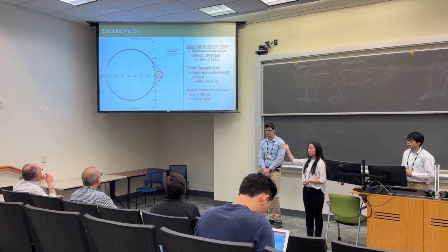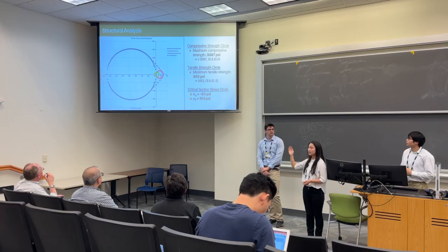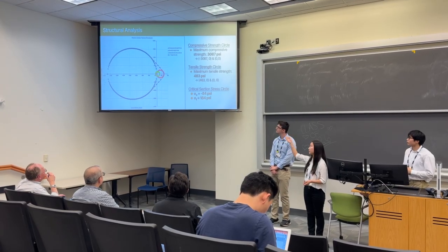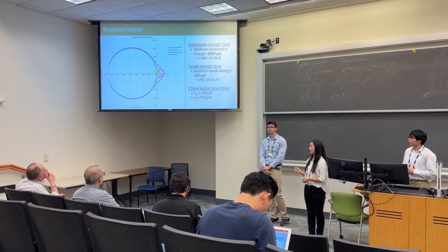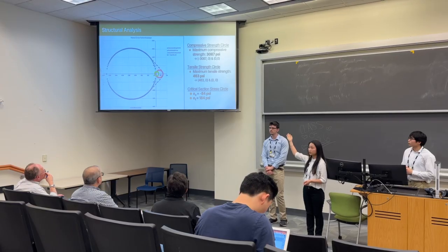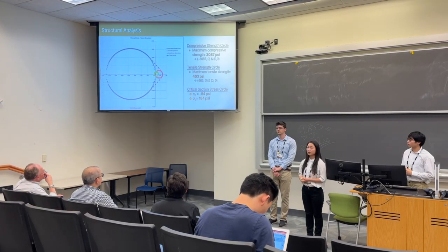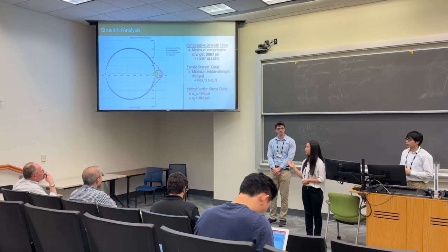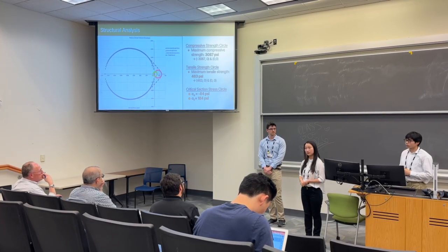And as you can see from our Mohr circle analysis, the maximum compression value is around 3,000 psi, and the maximum tensile value is around 450 psi. And our critical section stress circle lies well within the tangent bounds, meaning our canoe will be able to sufficiently handle the governing loads.